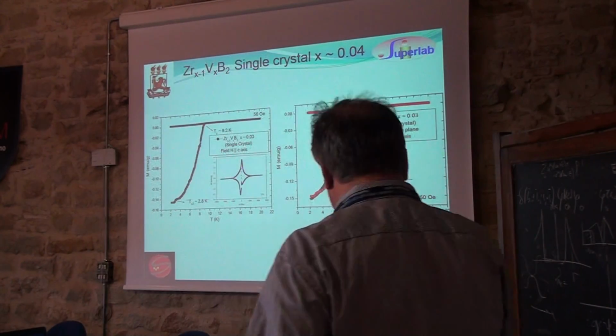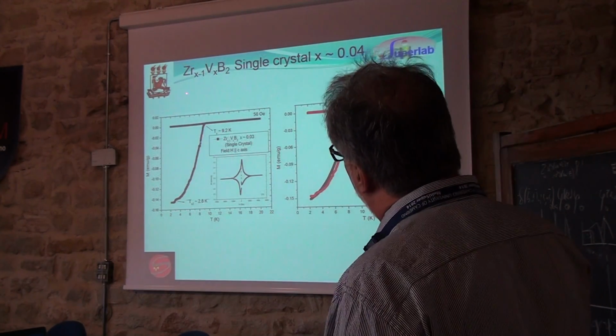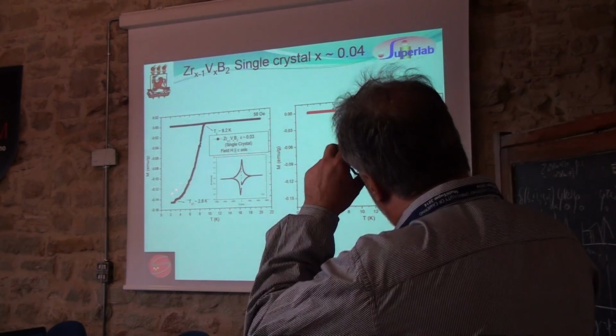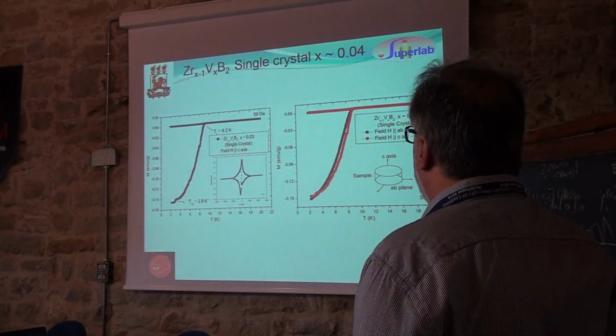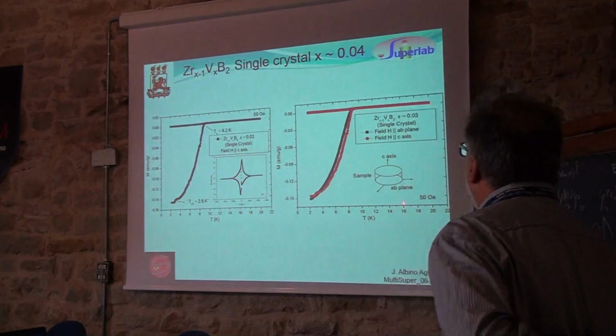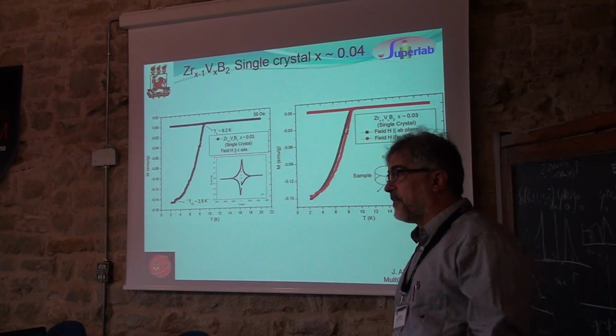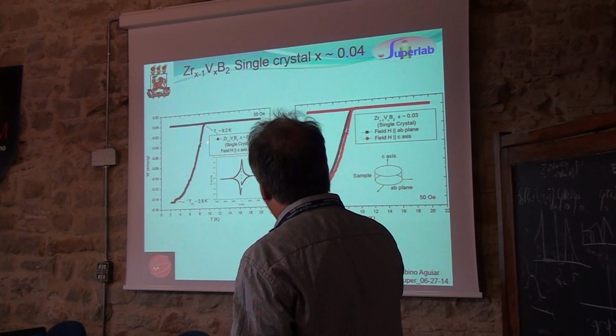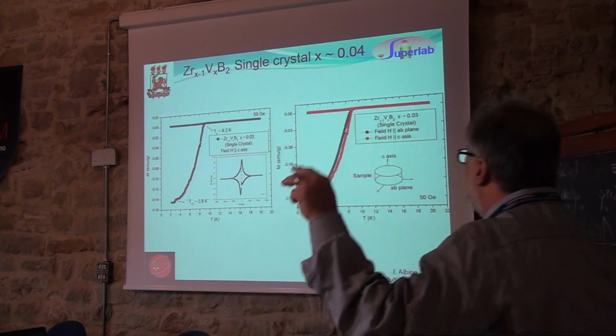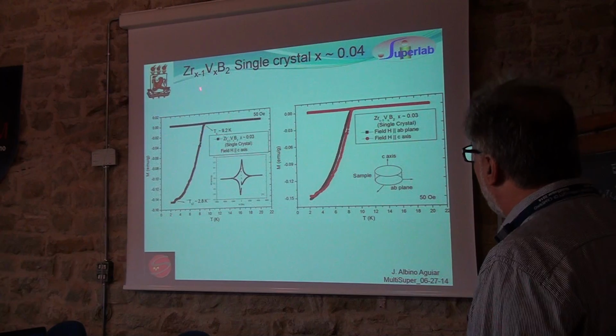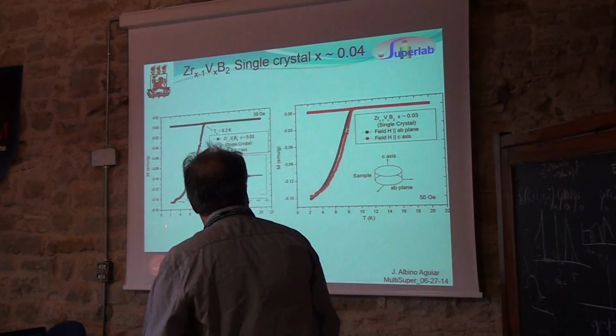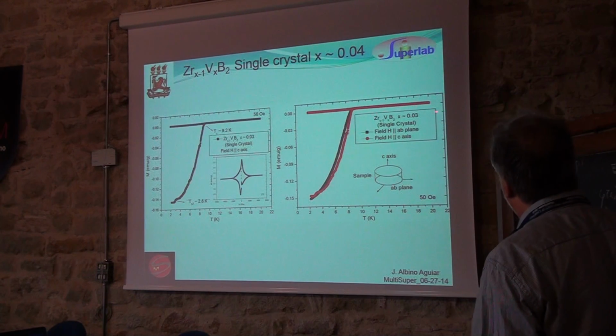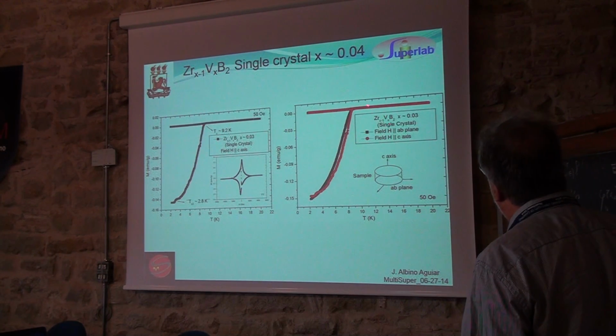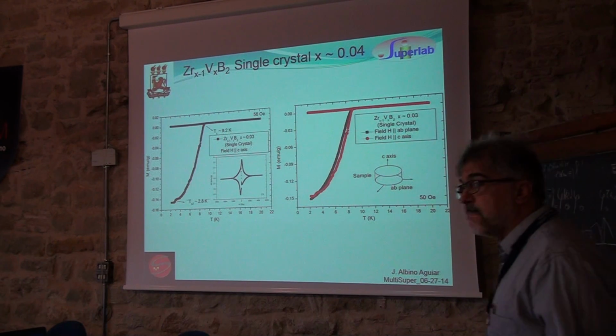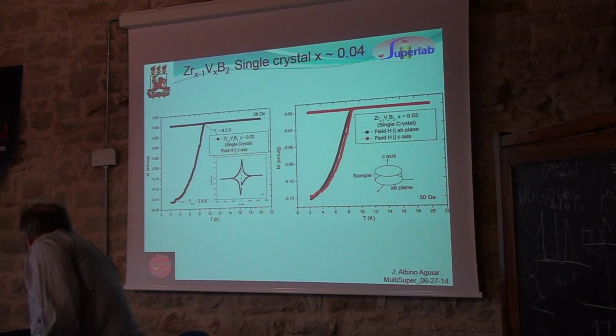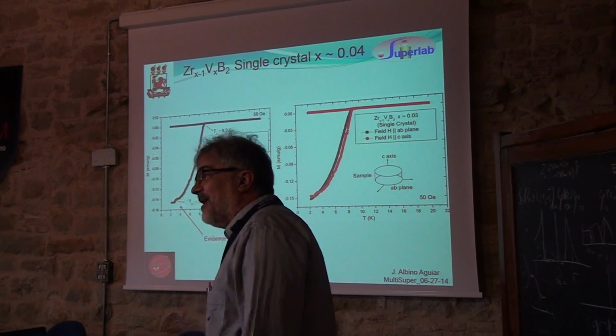So you have the temperature dependence of the magnetization as a function of field. When you apply the field parallel to the c-axis, on the left, you have a two-step transition. We claim that this is one transition, this is another transition. When you look here for the field parallel to the ab plane, you don't see it. Okay. So, our question is this.